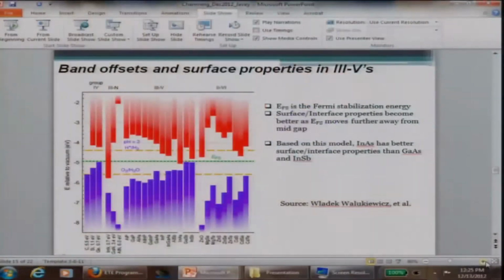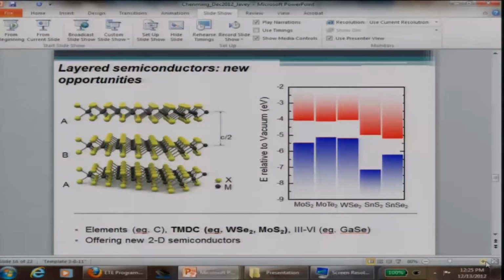And remember, we really only care about those defects, those traps that are in the middle of the band gap, at least for the subthreshold swing part. So this tells you why indium arsenide has good surface properties, at least from the subthreshold swing analysis point of view. It works in our favor. So when choosing a material, not only do you care about the conduction band and valence band and their location and the band gap, but you should also think about choosing a material that has pretty good surface properties by looking at the location of EFS.